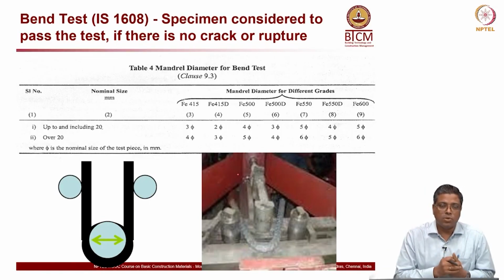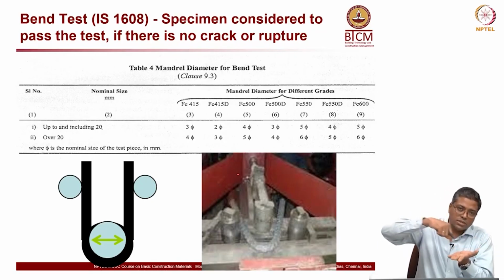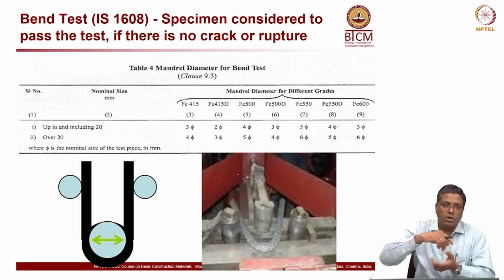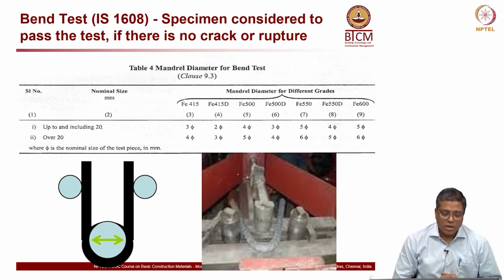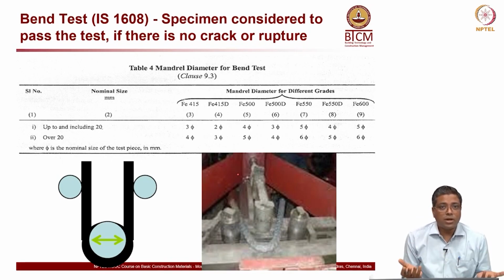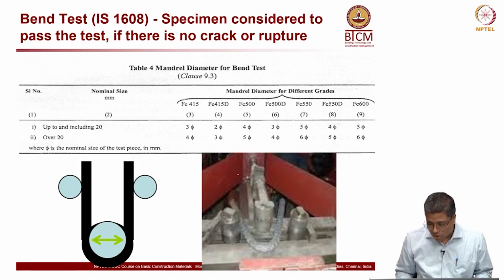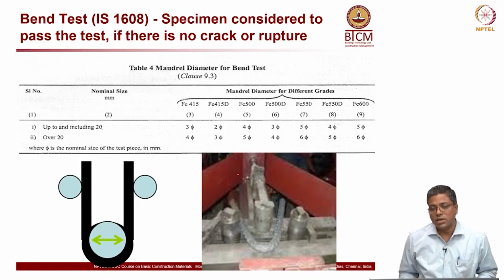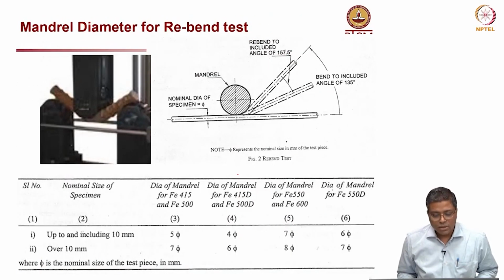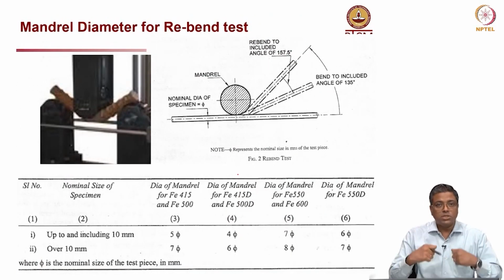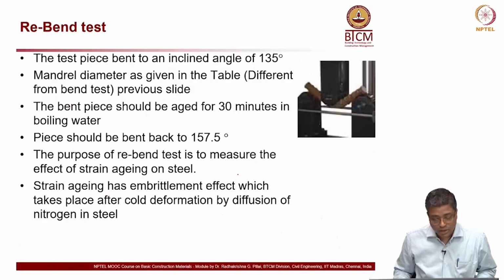For ductility requirements, you will have stirrups, which is the bar which goes around and which are bent, and those bars, when you bend, it should not crack. If it cracks, then it is not good. We discussed that in the previous lecture on TMT steel. If the coating is not good, then it will crack. And then people actually do this bending test and then see whether it cracks or not.